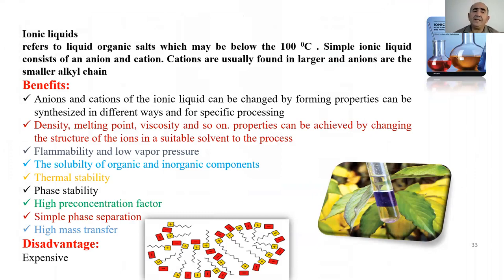And then another kind of solvents, ionic liquids, are like organic salts, and they have one cation and one anion site. They are used in different parts of chemistry. We used ionic liquids for the liquid phase microextraction of organic and inorganic analytes. Because they are thermally stable, their stability is very good, we can get a high preconcentration factor, and high mass transfer is possible, but the main disadvantage of these materials is that they are expensive.